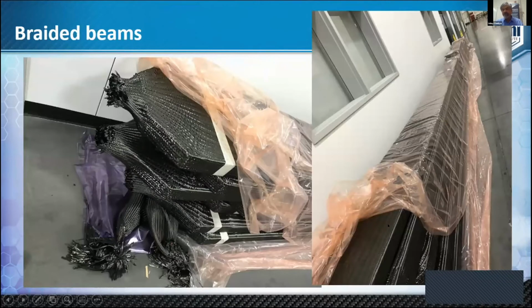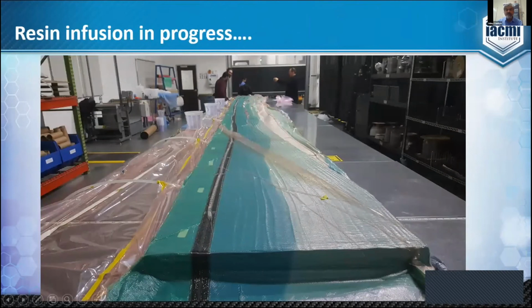We produced close to 20, 25, where we made a lot of mistakes in a few, but then these preforms were staged and would go through the vacuum infusion process. In a single step process, we were able to infuse this in about 20 minutes per beam. So very fast infusion, but the layup does take much longer than that, of course. We were able to get full consolidation and wet out through the infusion. This is an epoxy resin used over the braided architectures here.